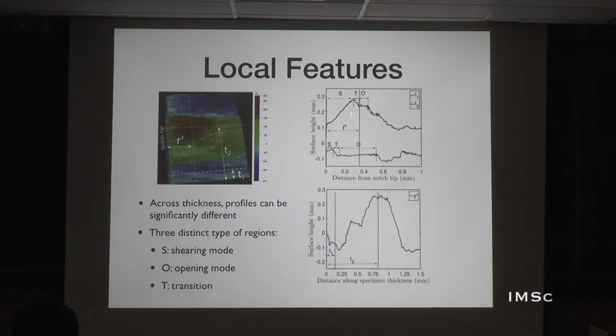So this is the location of the maximum roughness that we were talking about. What we are trying to say here is that during those 10 to the power 4 cycles of initiation life, there is a lot of activity happening near the notch tip. It is not necessarily restricted to fatigue damage in shear mode alone. It is also in tensile mode, acting very close to the surface but subsurface.